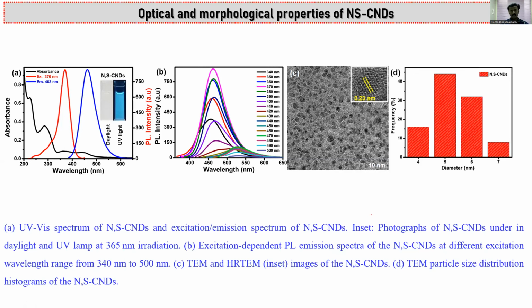From these studies we can confirm the particles are well dispersed in water without any aggregation. Most of the particles are not aggregated, and we can also confirm the lattice spacing of 0.23 nanometer, again corresponding to sp2 carbon. From the above morphological evidence and statistical analysis, I measured about 100 particles, and there is a narrow size distribution from 4 nanometer to 7 nanometer. The maximum average is 5 nanometer for these carbon dots.